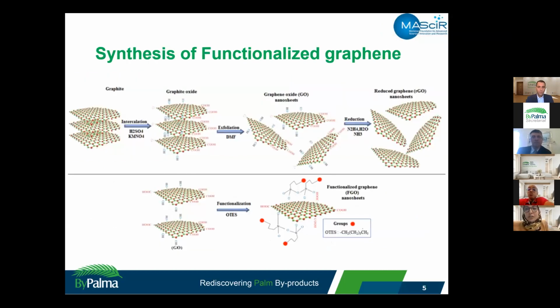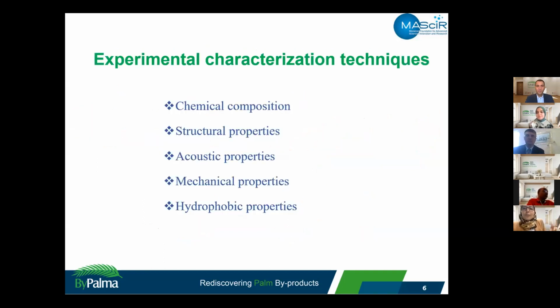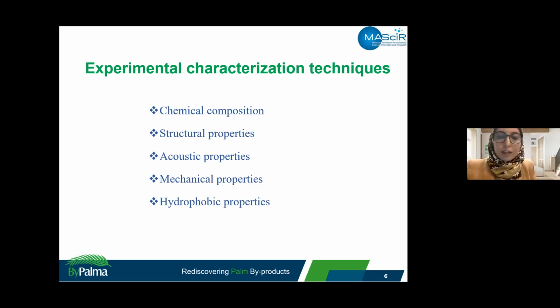The graphene oxide nanosheet was prepared by the vigorous oxidation of graphite powder according to the Hummers method in 2 steps, including intercalation process and exfoliation by sonication. For the functionalization of the graphene oxide surface, the octyltriethoxysilane (OTES) coupling agent, as a long chain grafted silane molecule, was added to the graphene oxide colloidal solution and heated under mechanical stirring for 2 hours at a temperature of 70 degrees Celsius. Therefore, the prepared graphene oxide and the functionalized one was washed and dispersed in ethanol solvent. The prepared composite was characterized by chemical composition, structural properties, acoustic testing, mechanical and hydrophobic tests.